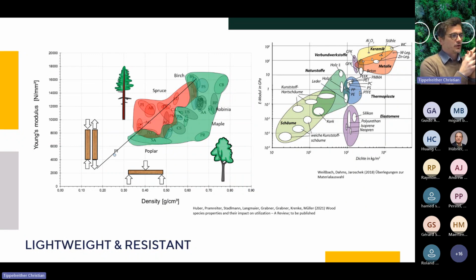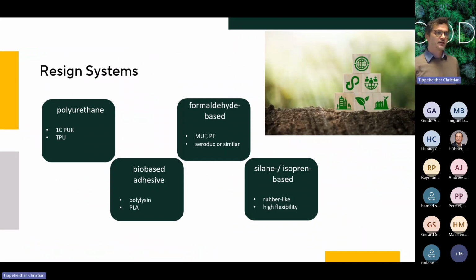So we are on quite a good way to produce this in 3D pressed parts, taking in some resin system. This resin system for gluing the thin veneers can be polyurethane, formaldehyde-based systems, or bio-based systems, or even rubber-like or something else with a high flexibility. Mainly it depends on the function which the customer or product needs, especially when we look at the railway sector, which is a quite big focus for us. Of course, you have some limitations regarding burning issues and so on. But there are several resin systems which are working in a good way, and we have our certificates for some products in this case.